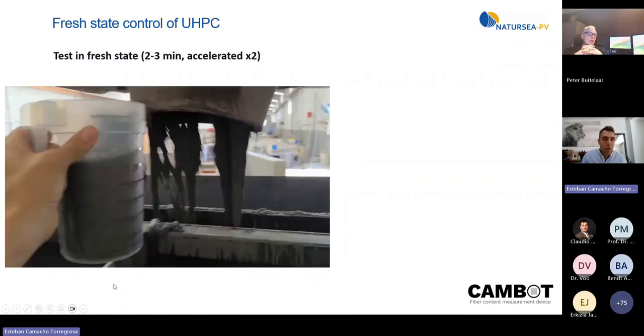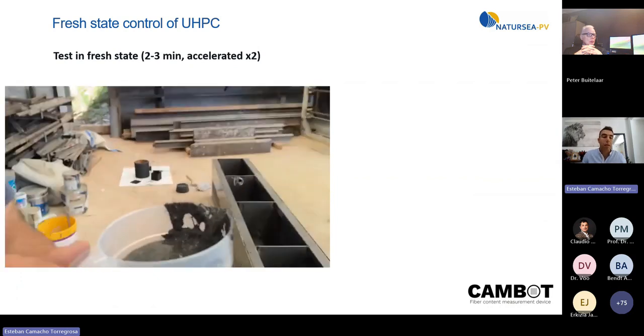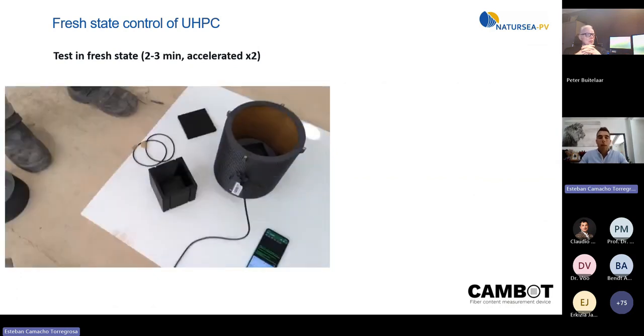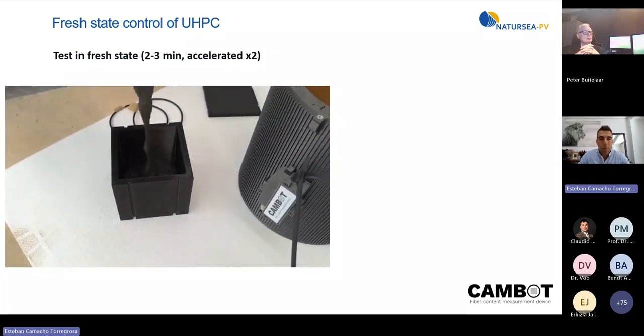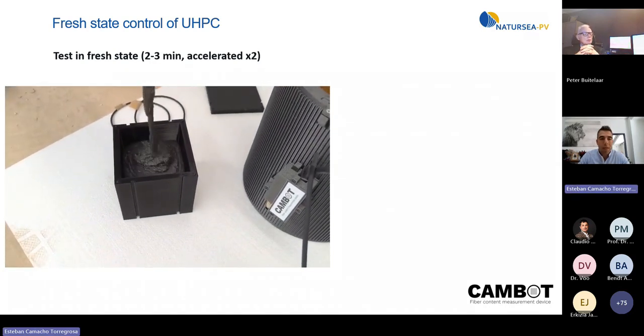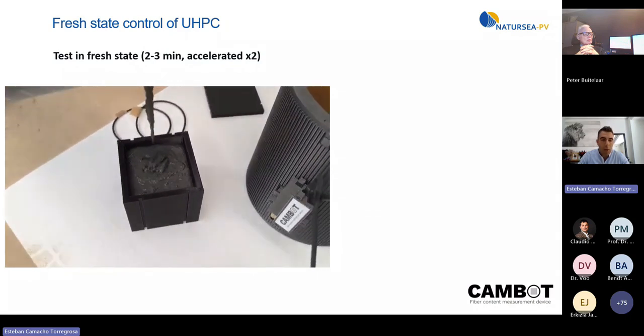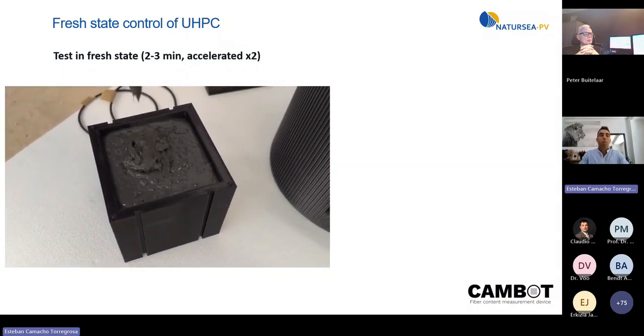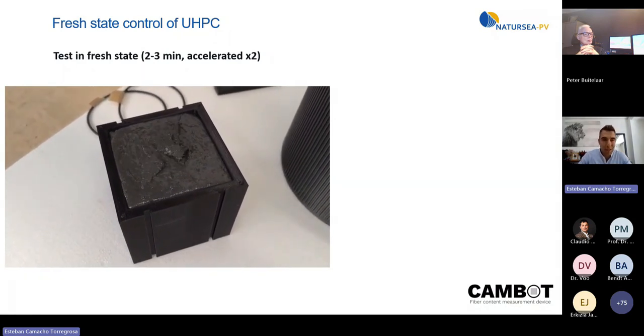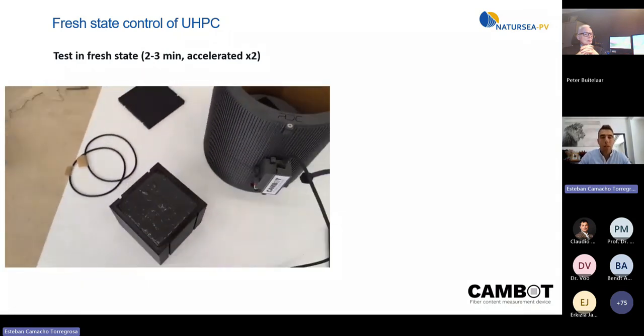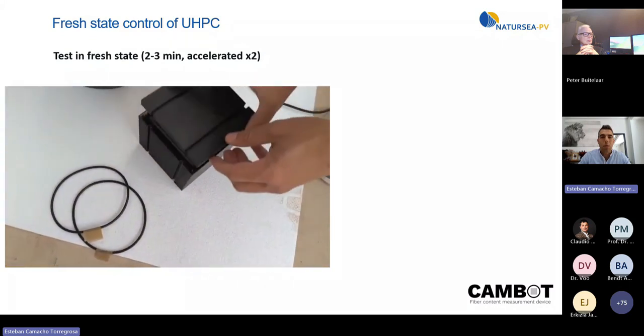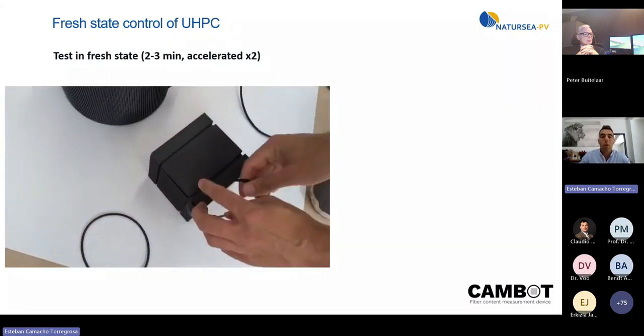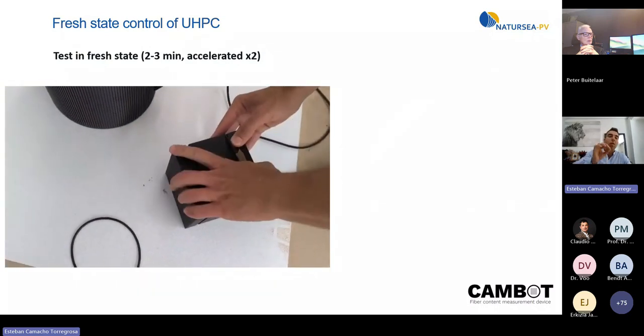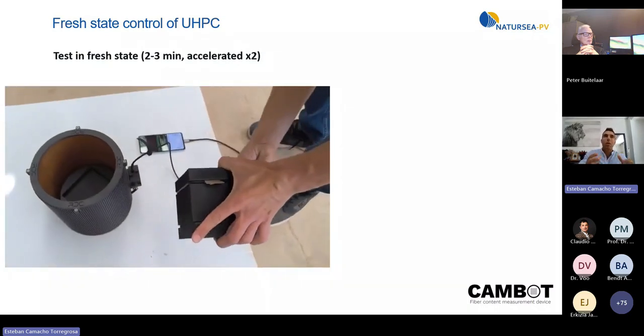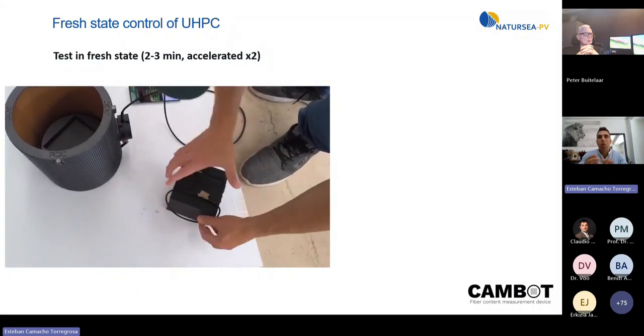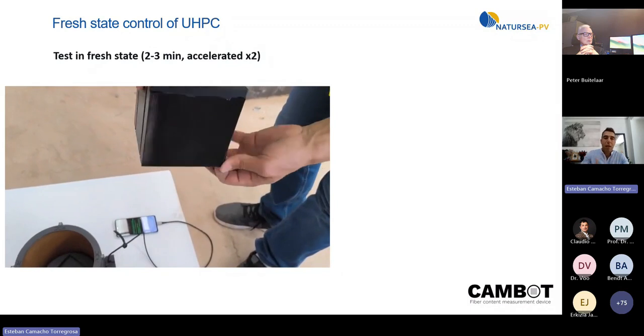This video is accelerated, it's multiplied by 2, but in the end, the test takes 2 or 3 minutes. We fill with fresh concrete a cube, which has internal dimensions of 100, 100, 100. We close it because we need that the material doesn't move, and introducing it in this device, which is connected to a mobile phone, it will tell us the inductance in each of the 3 directions. So in the end, it will provide the sum of the inductances of the fibers in each direction.